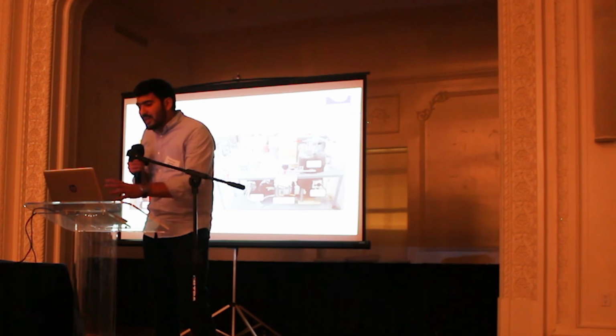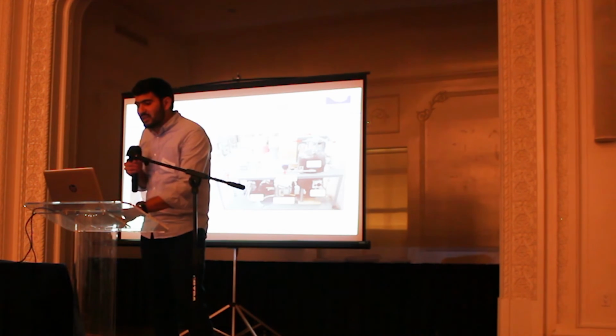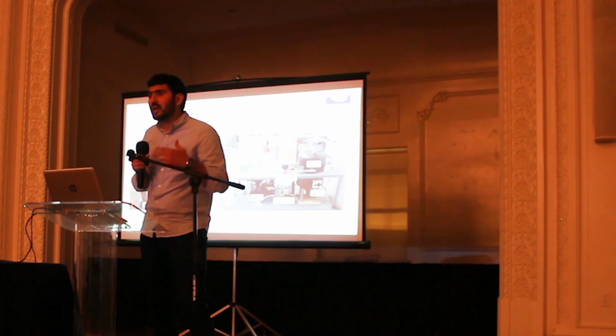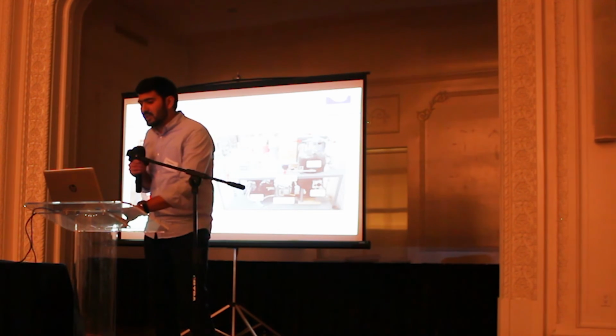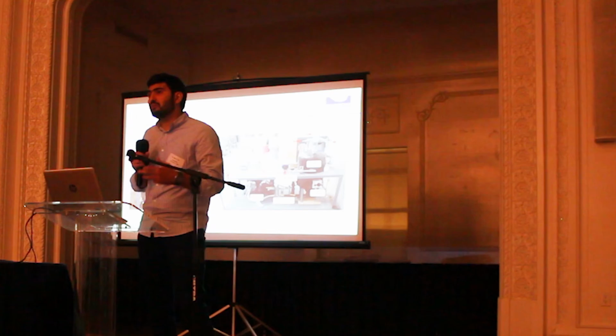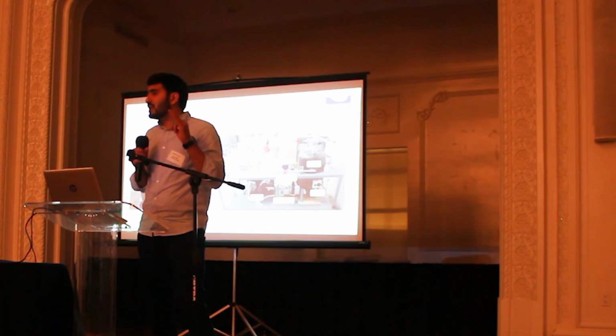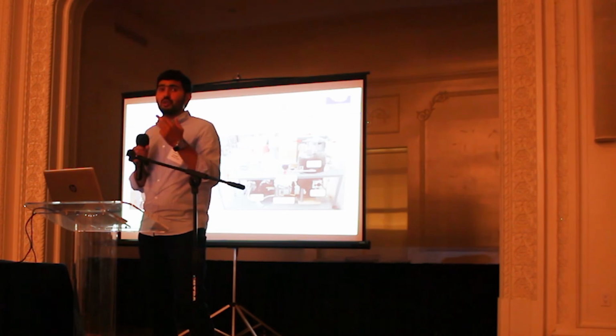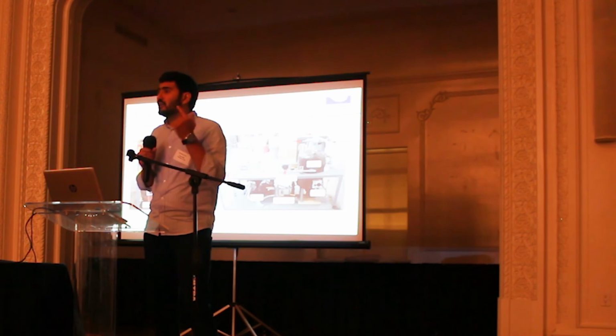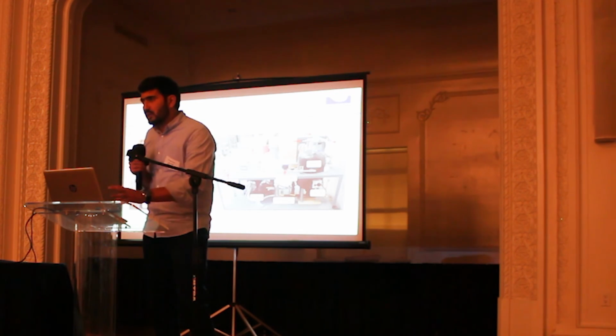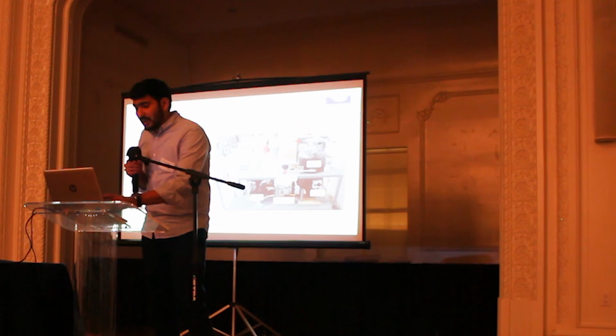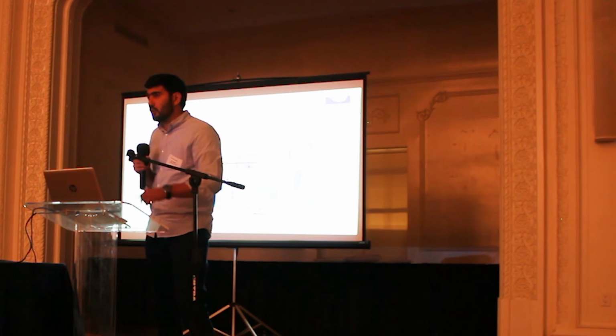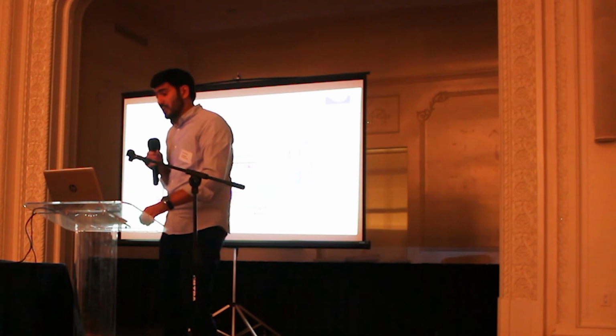But the main difference between the two is that this flow loop can have 1 test at a time, but in the 3-cell system we can run three tests at the same time, for example, erosion, corrosion, and erosion corrosion. So this is the main difference between the 2 testing facilities. Here we can see a schematic of the single test cell erosion corrosion flow loop testing facility.